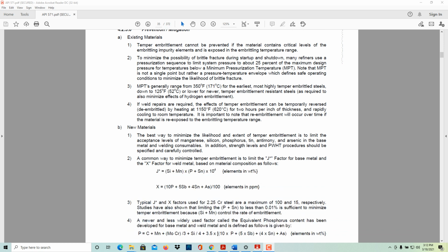Prevention and mitigation. Existing materials. Temper embrittlement cannot be prevented if the material contains critical levels of the embrittling impurity elements and is exposed to the embrittling temperature range. To minimize the possibility of brittle fracture during startup and shutdown, many refiners use a pressurization sequence to limit system pressure to about 25% of maximum design pressure for temperatures below a minimum pressurization temperature. Note that the MPT is not a single point, but rather a pressure temperature envelope which defines safe operating conditions to minimize the likelihood of brittle fracture.